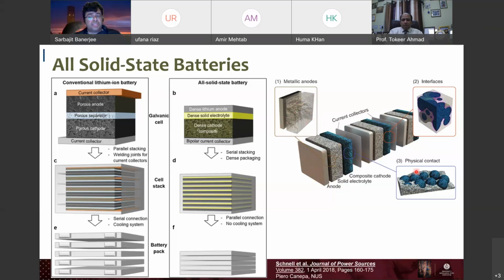The other important challenge, a big challenge in a solid state battery, is that lots of electrochemical reactions take place at the interfaces between the cathode and the solid electrolyte, and the anode and the solid electrolyte. There is a need to maintain physical contact as these things expand and contract with charging and discharging. This is a big problem, and it is typically handled by having a large stack pressure that holds these in place. But this is a major issue because there are very large volume changes going on during cycling, and it's important to keep physical contact.